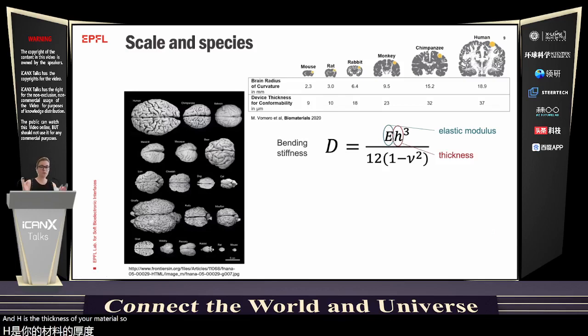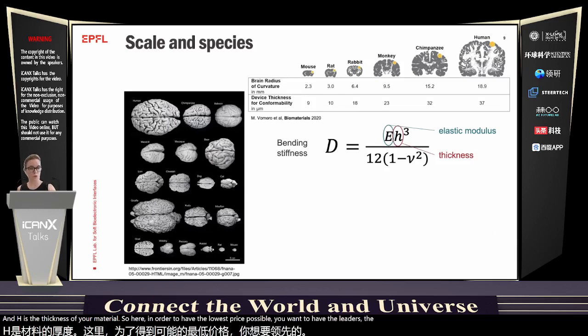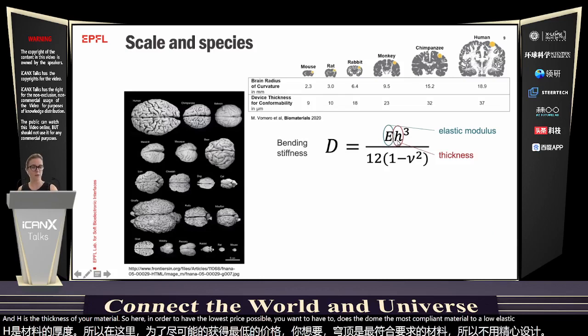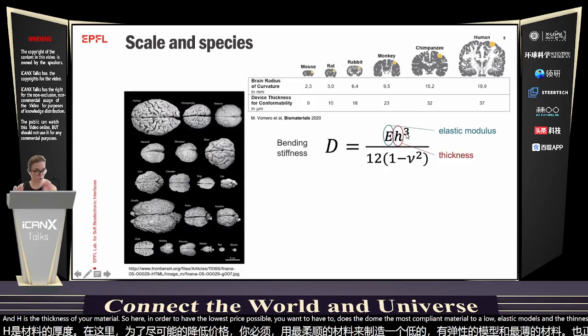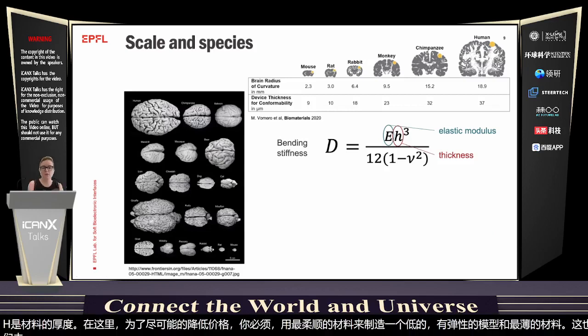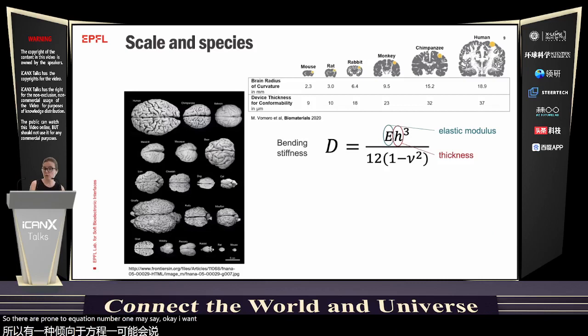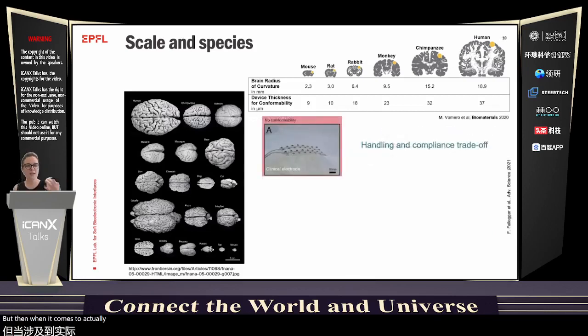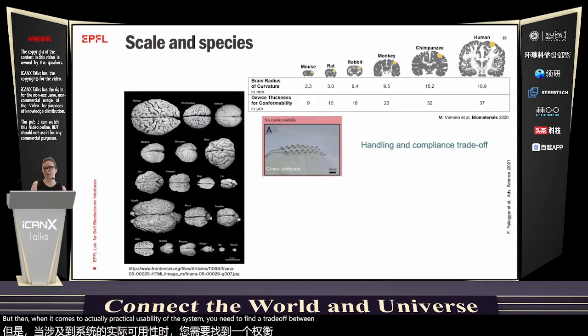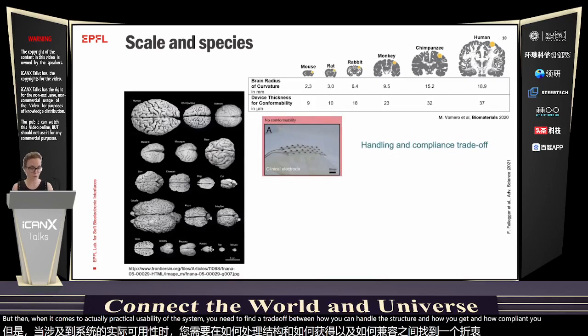In order to have the lowest stiffness possible, you want the most compliant material, so a low elastic modulus, and the thinnest material possible, because the thickness parameter is raised to the power of 3, so your bending stiffness will drop quickly. From the equation, one may say, okay, I want the softest material in the thinnest format. But when it comes to practical usability of the system, you need to find a trade-off between how you can handle the structure and how compliant you want it to be.